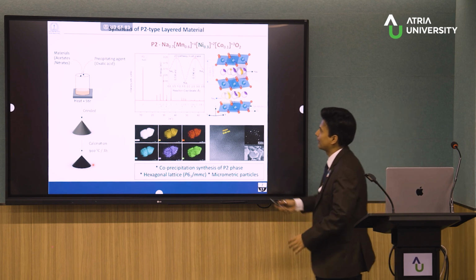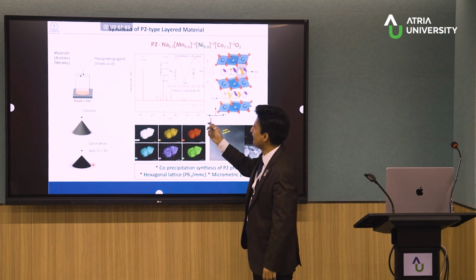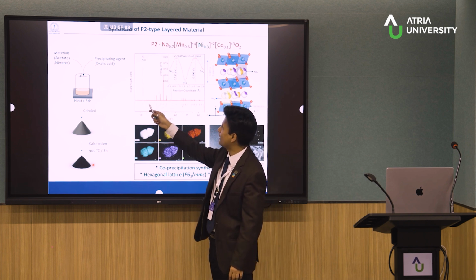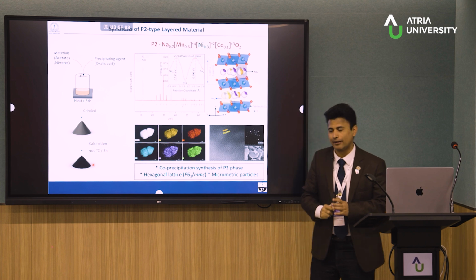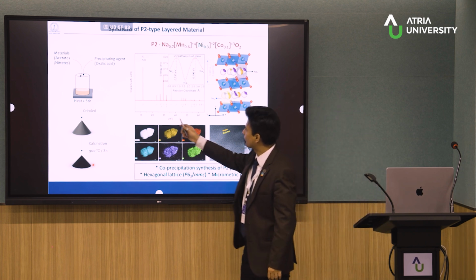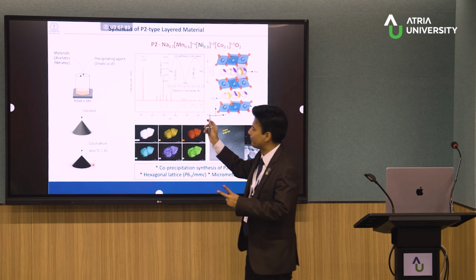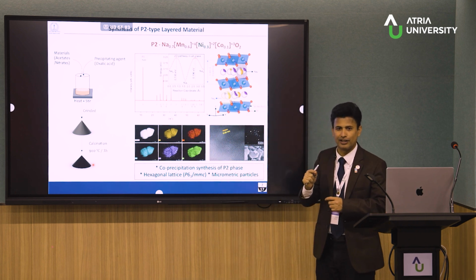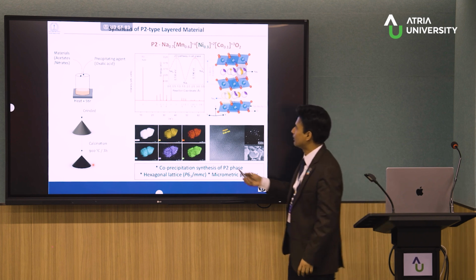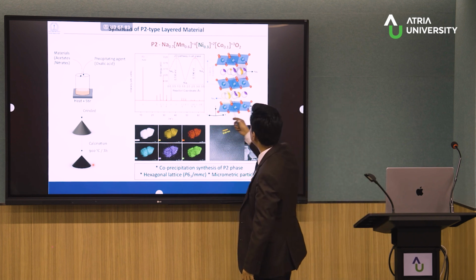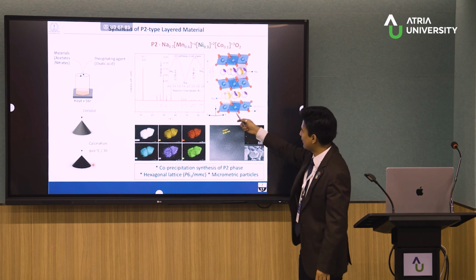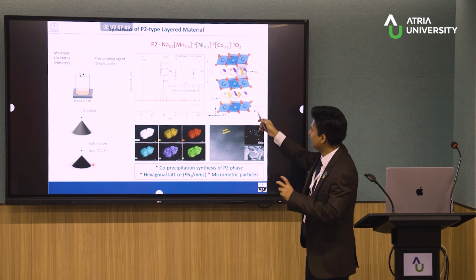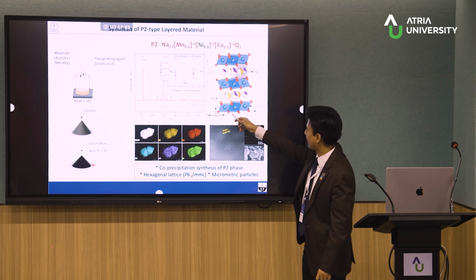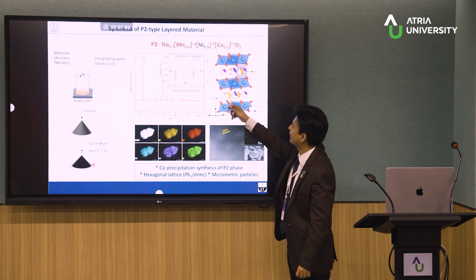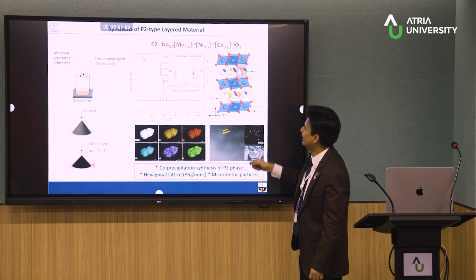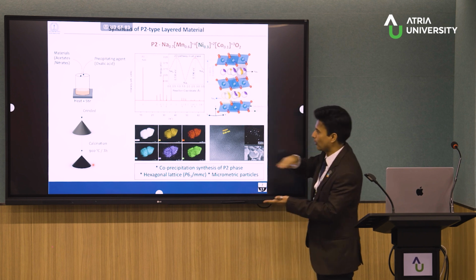So this is the synchrotron XRD we have done at Thailand synchrotron BL1.4, and there you can see very high intensity nice peaks, all corresponding to the P2 kind of system, the classical system, and we have some secondary phase about 2-8%, which is basically some kind of nickel oxide, which is very, very stable and we cannot avoid it. So this is the structure. Again, this is the P2 kind layered structure. In the transition metal, rather than only manganese, we have manganese, nickel, cobalt. Mostly it is manganese, and this is the sodium, sitting in the P2 prismatic kind of site. Here the interlayer distance is very, very high, so sodium can move easily.